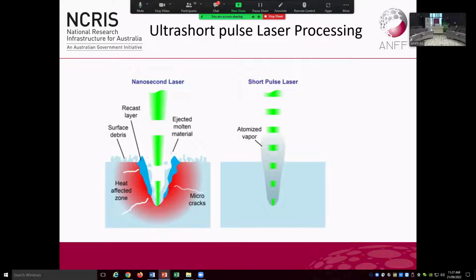And I've got 3 of them just to show you an example. This is one. They talk about having a nanosecond laser, so a laser with pulses of tens of nanoseconds. Tens of nanoseconds is enough to conduct heat into the material over the duration of the laser pulse. And so what they often say with nanosecond lasers is you're going to make a mess. You're going to end up with recast material and surface debris. We're talking about lasers which get down to 10 picosecond and lower pulse, where the process is largely more, like I was describing, the coulombic explosion, can be more dominated by ejection of atomized vapor rather than actual phase change in the material.